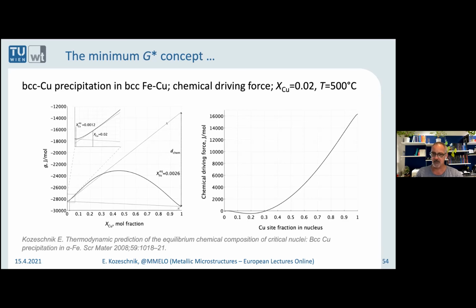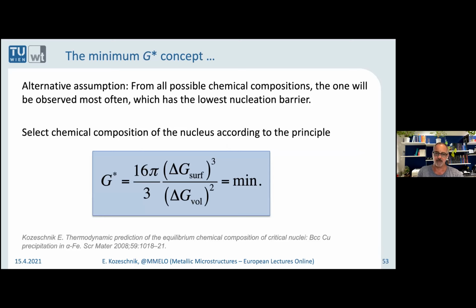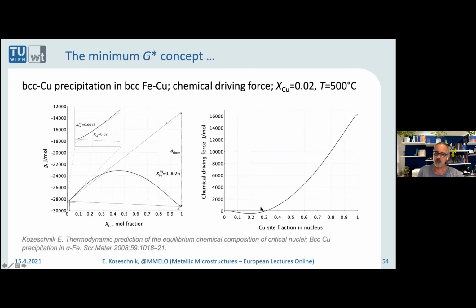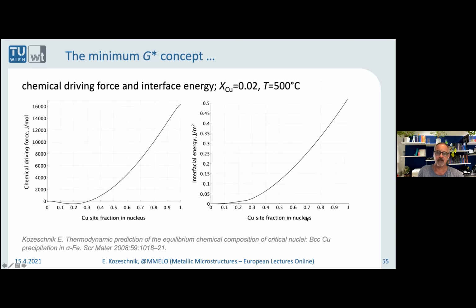So the next problem was simply, how can I calculate the nucleation barrier from my knowledge? What I need is information on the surface energy, gamma, and information on the driving force. The driving force I was already showing you. This is a function for the driving force as a function of nucleus composition. And this is now the interface energy calculated as a function of the composition of the nucleus. And you can see that it is increasing with the copper content of the particle. So basically, theory gives you the approximation that the interface energy should be proportional to the square of the copper content difference between matrix and particle.